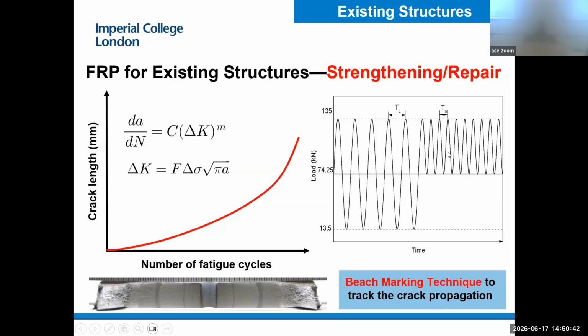So we used a technology called beach marking technology. This is the fatigue cycles - we use a greater, larger stress range, and after a number of cycles we reduce the stress range, and we repeat this loading pattern. Why did we do it?